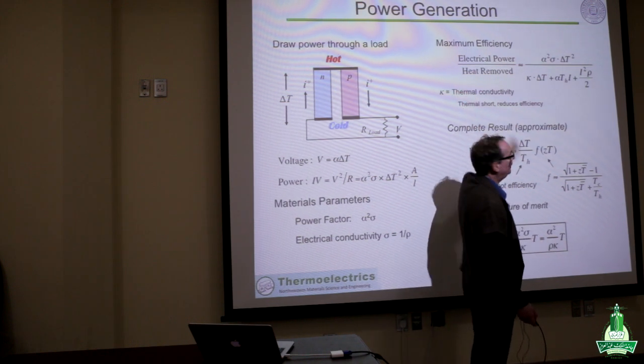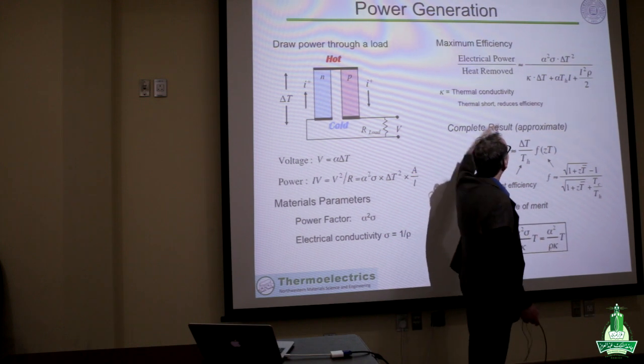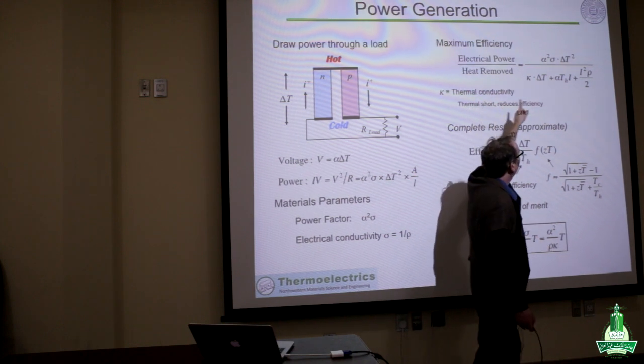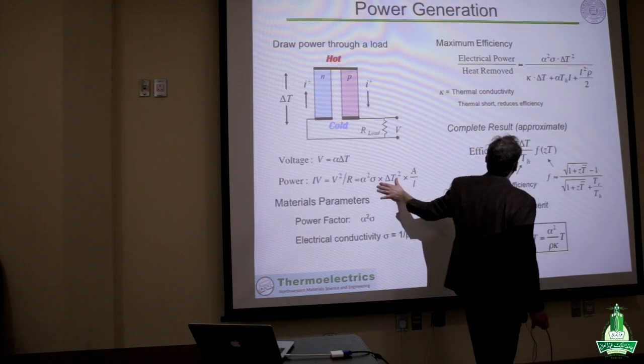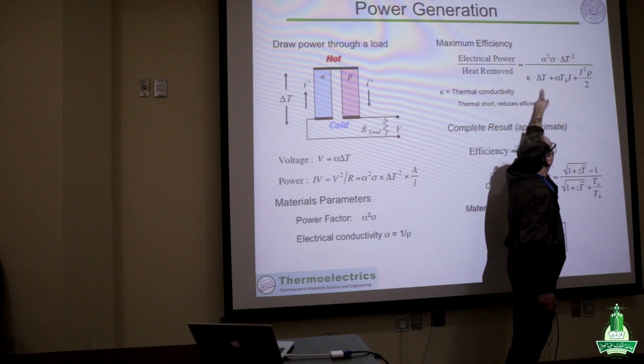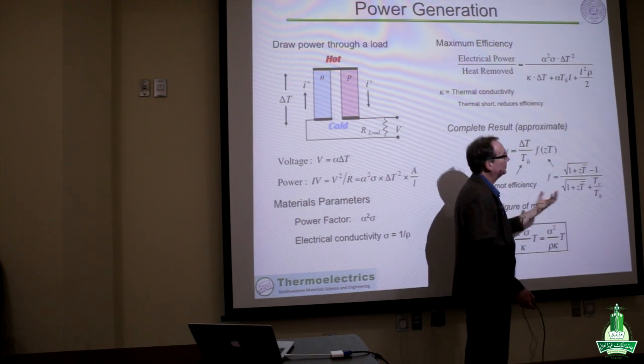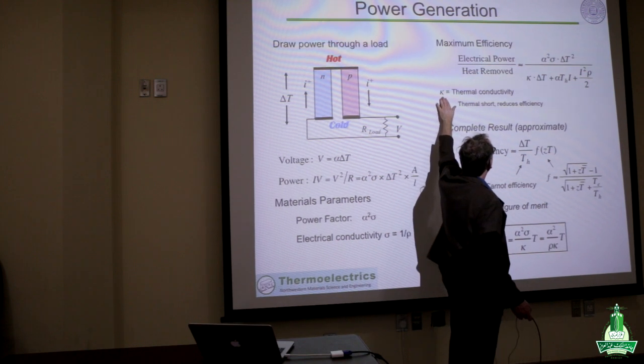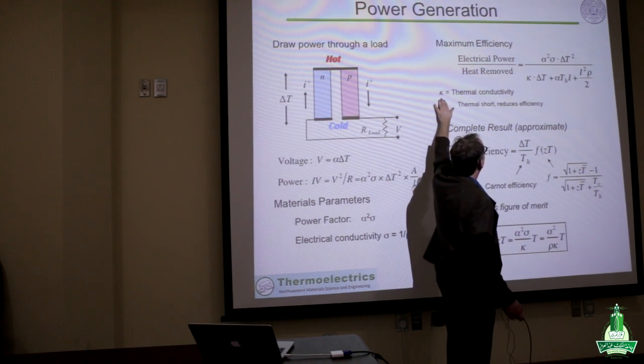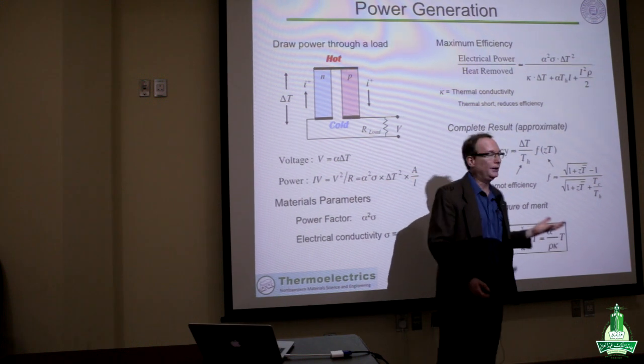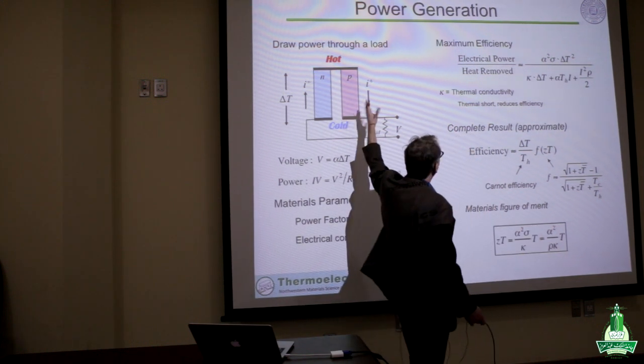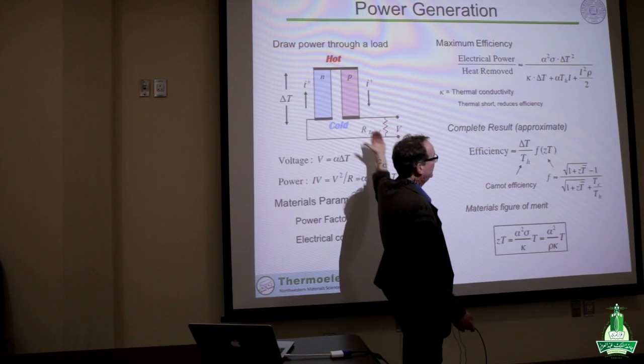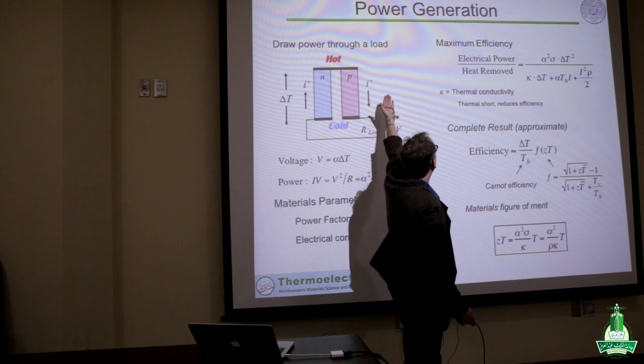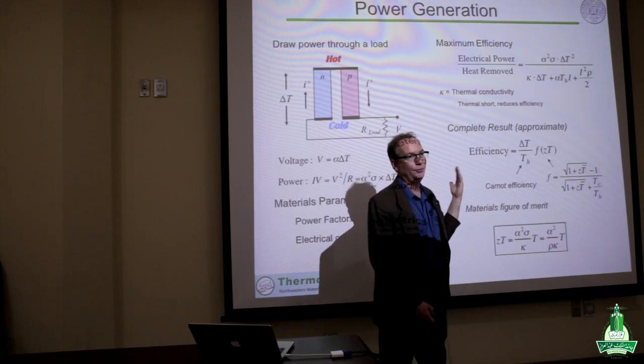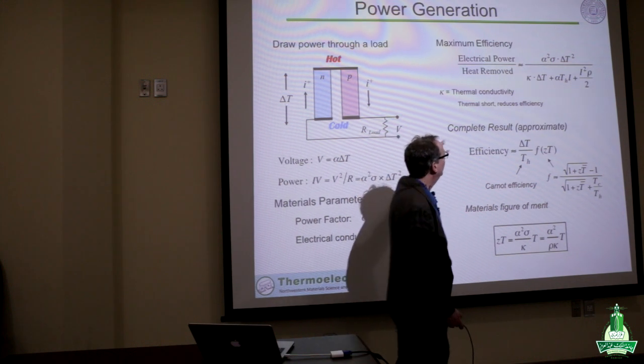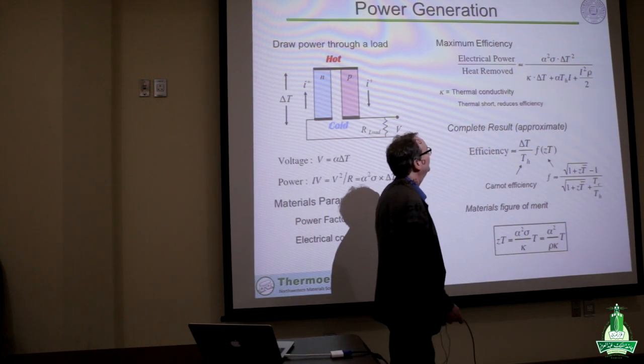So efficiency is power out divided by power in, which is our electrical power, which we had from before. But from the heat removed part, the most important parameter we bring in is the thermal conduction, where we characterize the thermal conduction through the thermal conductivity. I like to think of this as, if our material has a very high thermal conductivity, it acts as a thermal short where heat is quickly conducted from hot to cold. If we conduct heat from hot to cold without producing electricity, that will reduce our overall efficiency.